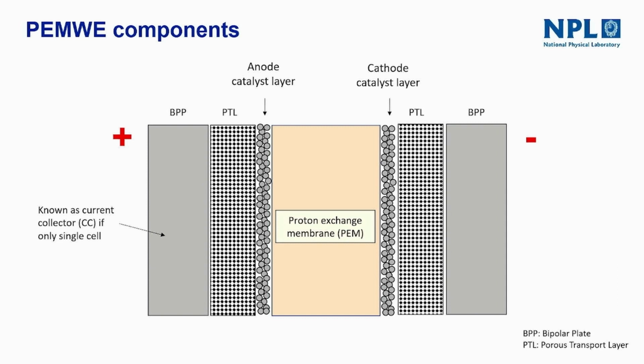And just to give you a framework for the work, you apply a voltage across this cell, and with respect to the hydrogen electrode, the potential of the anode electrode is about 2 volts during operation, and the cathode is about 0 volts because it's generating hydrogen, so it actually acts like a hydrogen reference electrode. And the common assumption all across industry and throughout academia is that all of these materials on the bipolar plate and the porous transport layer sit at this potential of 2 volts during operation. And for those corrosion scientists, and particularly cathodic protection scientists and engineers in the room, you will know pretty much straight away that because this porous transport layer contains deionized water, this 2 volts does not transfer across to the bipolar plate. It's analogous to throwing power in CP, that the bipolar plate will actually sit at its open circuit potential and will be effectively unaware that it's close to an electrode at 2 volts.